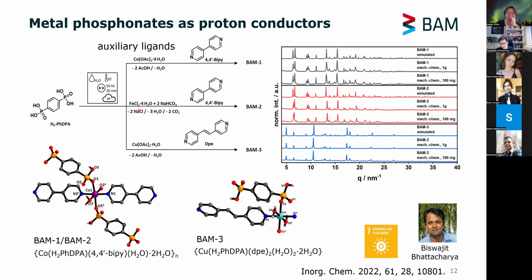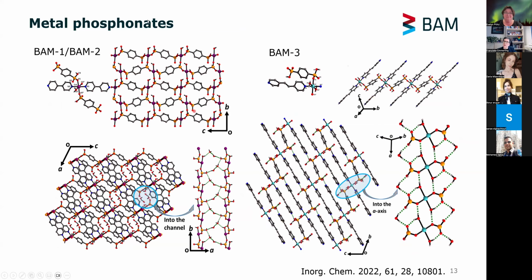Most of the time we go for something like an acetate, because then you already have someone to extract your proton. But nevertheless, you can see here the reaction is quite straightforward. In this case, it takes about 30 minutes, and you can easily make those in milligram scale, but also up to gram scale. It depends a bit on the conditions you choose in your mill. And here we also started to name our compounds BAM 1 and 3 and so on.